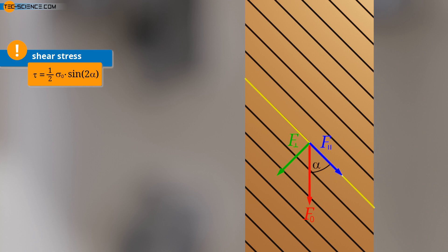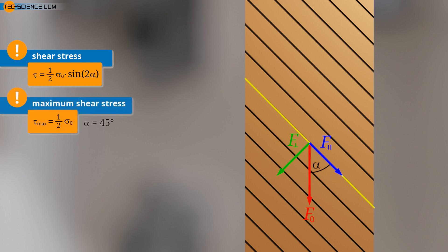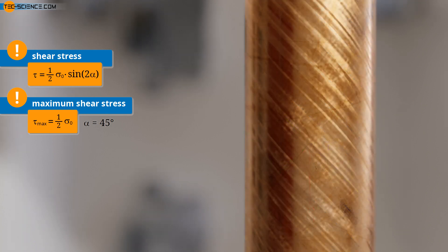The shear stress depends on the applied external stress sigma_0 and, in particular, on the angle alpha. The term sine 2 alpha reaches the maximum value of 1 for an angle of 45 degrees. It can now be seen mathematically that the maximum shear stress tau_max is reached at an angle alpha of 45 degrees, where the maximum shear stress is exactly half the external normal stress. For precisely this reason, the copper single crystal shown has slip steps at an angle of about 45 degrees to the tensile axis, provided the lattice structure is spatially oriented so that a slip plane results at that angle.